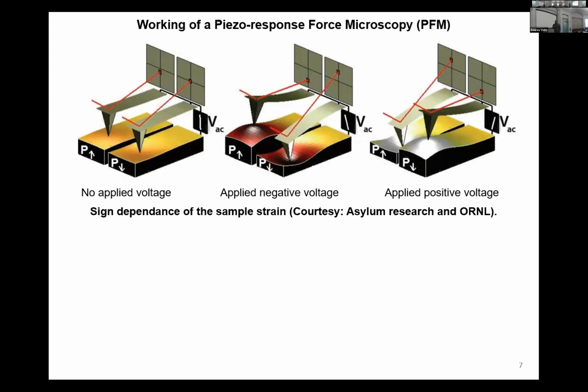So before we start, I would like to give you a glimpse of piezoresponse force microscopy. That's the technique that I have used throughout these experiments. In this technique, we have a cantilever which is in contact with the material surface. Now, ferroelectrics can have polarization pointing up or pointing down. When this cantilever is in contact with the sample, we apply an AC bias, and depending on the direction, the domains either expand or contract, due to which the cantilever moves up or down, and we track the movement of this cantilever using the photodetector. By this, we can map the ferroelectric domains in any material.